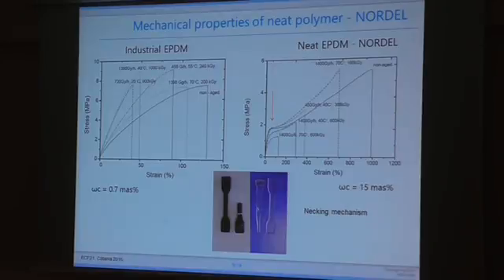Also, in practice, we can see the consequence of this necking process after our tensile test. You can observe the existence of necking, or narrowing, in the neat polymer, but the same is not observed for the industrial polymer. So it recovers its shape fully after the extension. Moreover, we can observe that with aging we lose this yield point, and for high doses, the neat polymer actually behaves like the industrial one. What is the origin of that? Probably destruction of the crystalline part, but this still has to be proven with some additional chemical analysis.